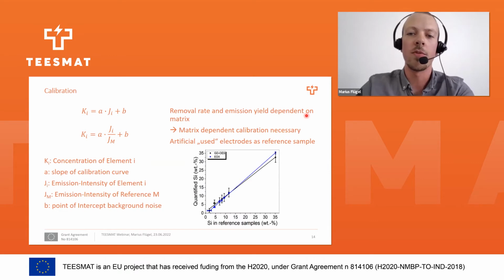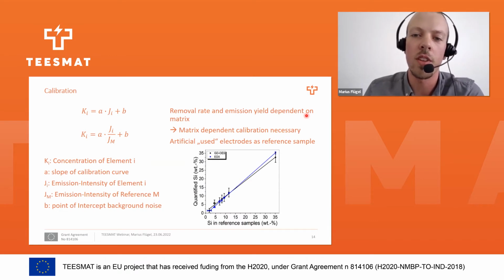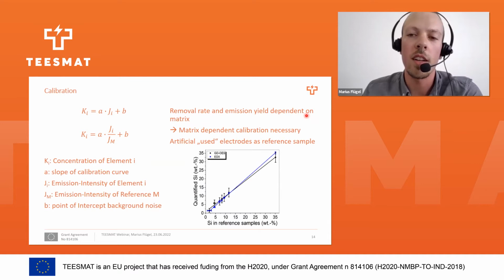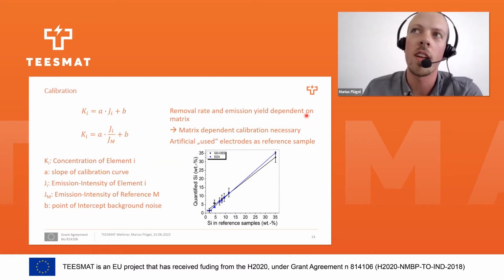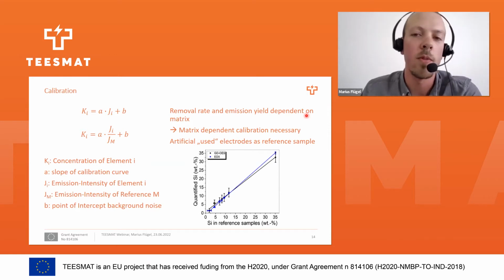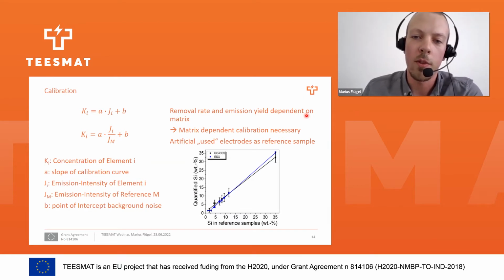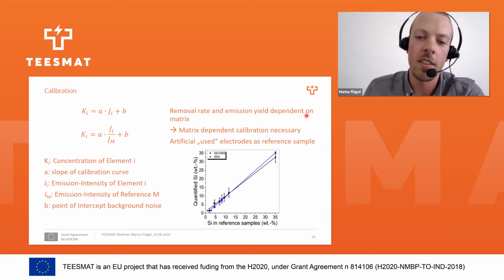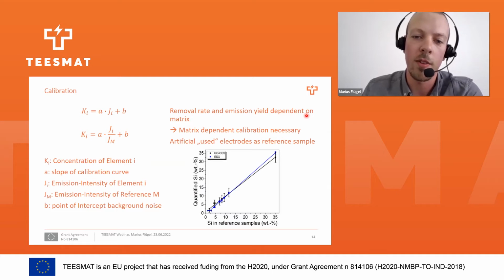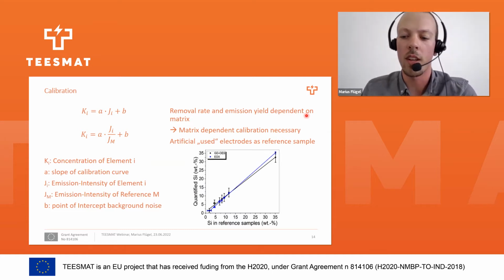For the calibration, we use artificial used electrodes. Those are electrodes that are prepared in the same way as real electrodes, but we add additives like silicon oxide, copper oxide, or lithium dihydrogen phosphate to introduce elements like silicon, lithium, or copper, which are not present in fresh electrodes. By comparison with, for example, EDX, we can see that with GD-OES, we can quite nicely quantify all elements.